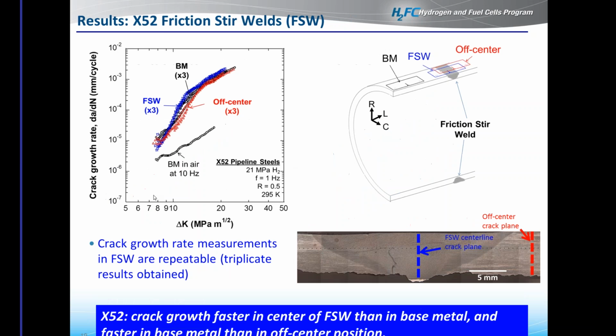Now we also looked at an X52 friction stir welded pipe, and as I show here in the schematic on the right, we looked at 3 different areas. The base metal, the blue is the center of the fusion zone, or center of the friction stir weld, I should say, and then the off-center region is shown in red. And as I mentioned before, the dashed lines represent the areas where the crack plane would be propagating through.